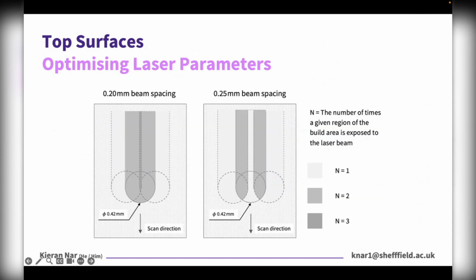And we attributed this to this mechanism, this double in situ laser scanning type mechanism that occurs when you employ laser beam spacings that are less than the radius of the laser beam. So we found that with lower laser beam spacings, so 0.2 millimeters in our case, we had this double scanning effect, whereas when we employed standard laser parameters, so employing a laser beam spacing of 0.25 millimeters, we only partially had this double in situ scanning.